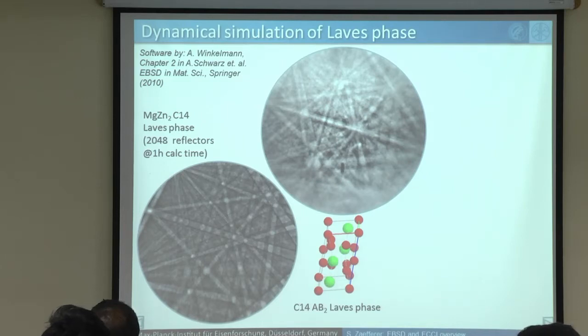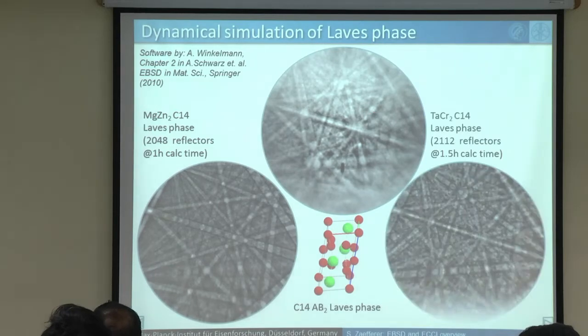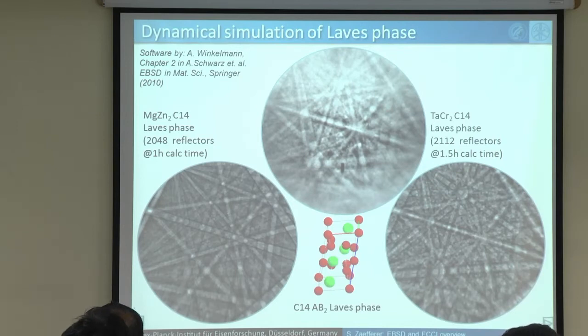No, but it's not the software which is not good, but it's my assumption that it's magnesium zinc which is not good. This is tantalum chromium Laves phase. So, and if you now enter the correct atoms here, tantalum and chromium, and calculate again, you see how strongly this changes. Geometry is exactly the same thing. I didn't change anything on the geometry. Yeah? I just changed the correct atoms. And you see now suddenly there is exactly this bright band in the center with the diffuse band around, and all the details which you have in this not so nice pattern are correctly reproduced.